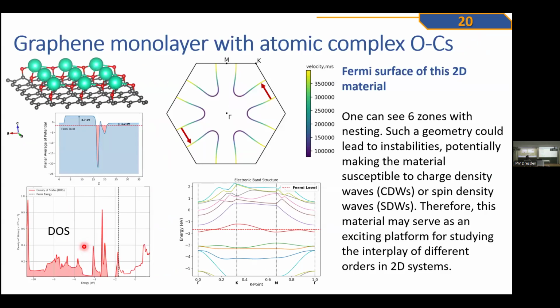We also investigated the two-dimensional material containing a graphene monolayer with the atomic complex oxygen cesium. The fact that this material is metallic and has an anomalous 1.2 electron volts work function suggests it could be a promising candidate for use as a tip in scanning tunneling microscopes, field emission cathodes, and so on.